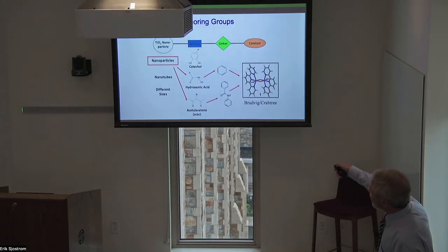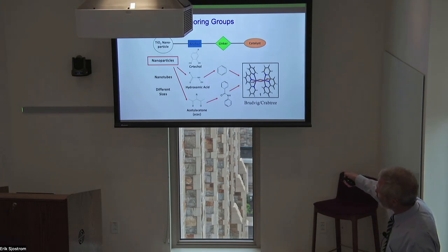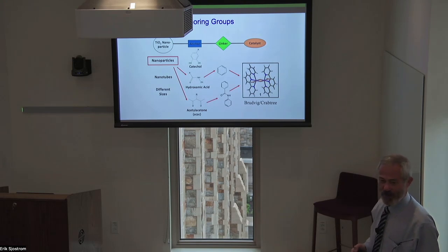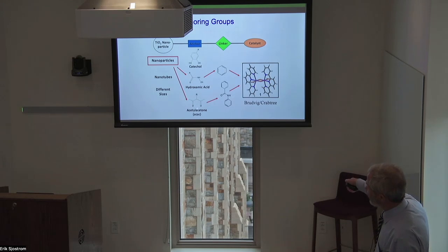Okay, so the anchoring attachment. For a metal oxide, you need a molecule that can strongly bind to the surface. So we have used in the past a variety of chelating molecules like catechol, which has this bidentate chelating group, hydroxamic acid, which is also bio-inspired. These types of molecules are synthesized by bacteria to sequester iron, and acetylacetonate, which is a well-known chelating group in inorganic chemistry. And these all have been good, but not completely satisfactory, in that they don't all have such stable binding.